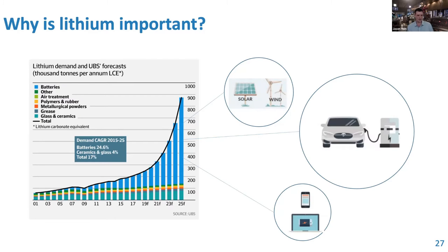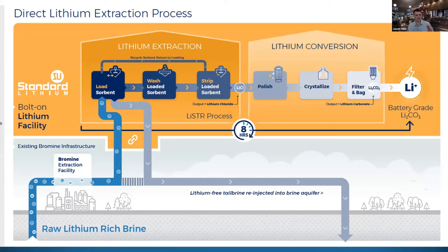Where I got involved specifically comes down to a collaboration we're doing with a local company here in Vancouver called Standard Lithium. Standard Lithium has made this direct extraction technology, where a plant in Southern Arkansas at a LANXESS facility is currently working on a bromine process where they pull up this lithium- and bromine-rich material, extract the bromine, and currently that tail brine would just be reinjected into the ground. Through a joint venture agreement, they created this new process where that tailing brine, now bromine lean, is passed through their sorbent process to get a stripped material and then returned back. That gives us a lithium chloride solution.